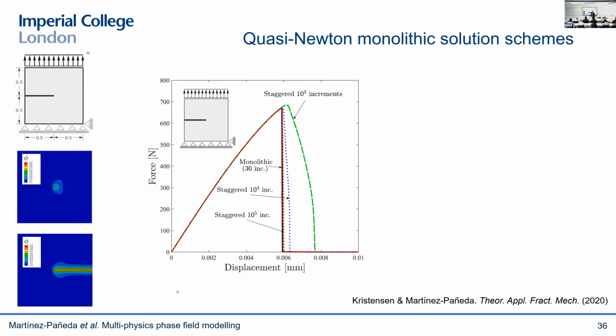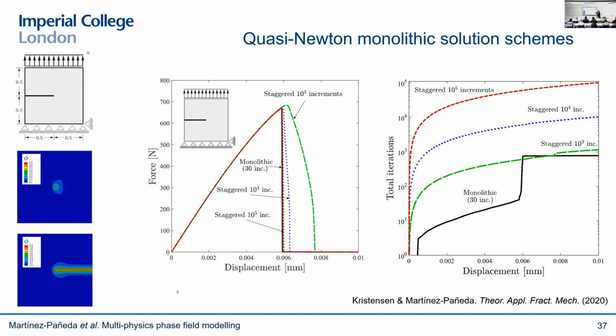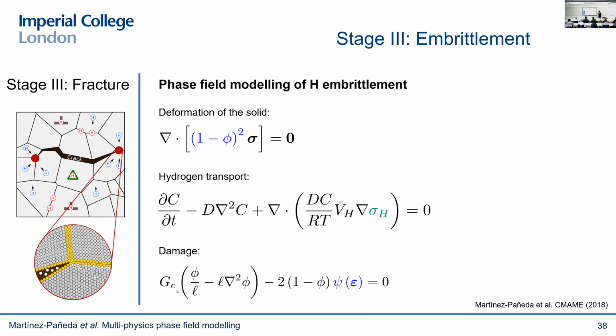So this unstable fracture problem, you can capture in seconds on your laptop, while these single pass staggered schemes require almost, I would say, 10,000 increments to be able to give you the right result. So when you count the total number of iterations, this means that you are using orders of magnitude more iterations when you're using these staggered schemes versus these quasi-Newton monolithic approaches. So we find them to be very powerful, and we're very happy that we came across this. And we use this, for example, for simulations where we're doing fatigue, where we do cycle by cycle, and we really need efficiency, and this can make a big difference to us.